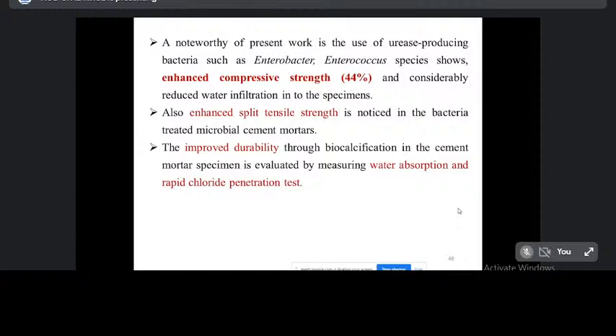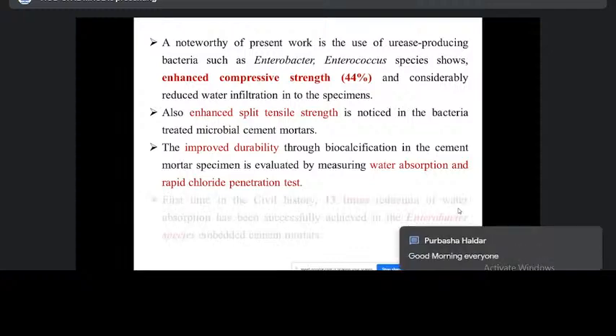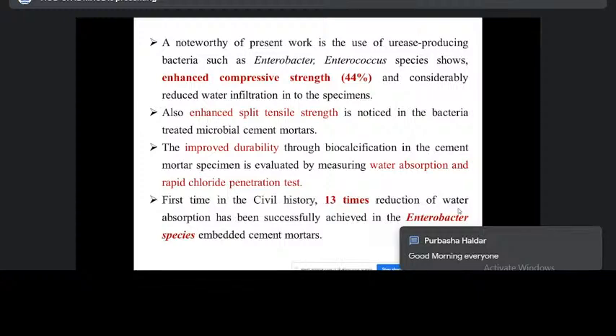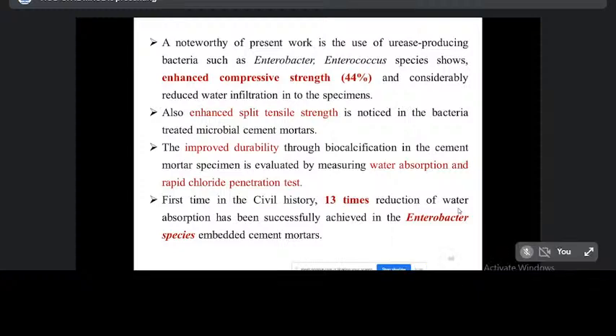The improved durability through biocalcification in the cement mortar specimen is evaluated by measuring water absorption and the rapid chloride ion penetration test. For the first time in civil history, a 13 times reduction of water absorption has been successfully achieved in the Enterobacter species embedded cement mortar specimen.